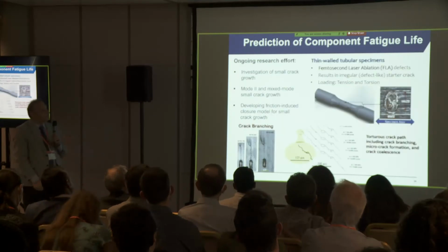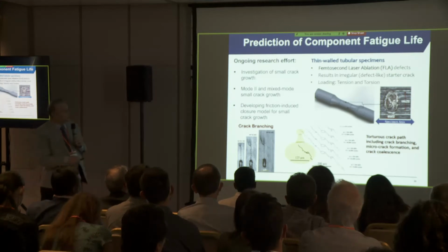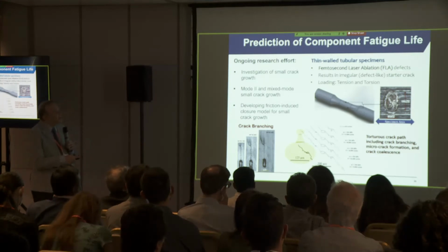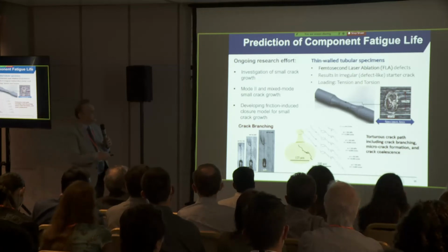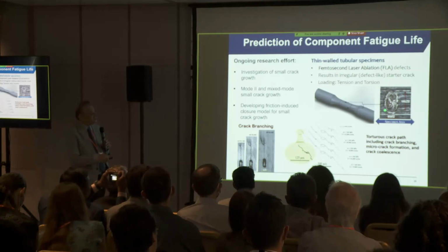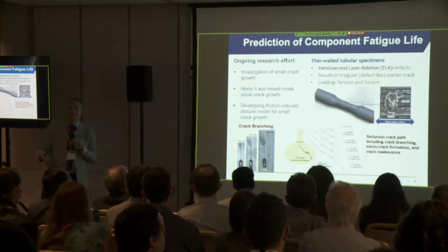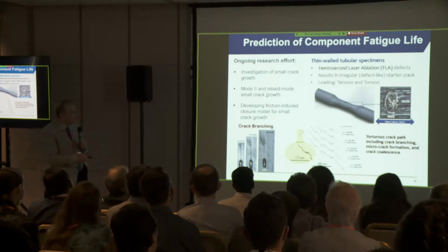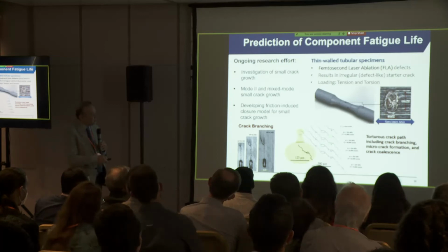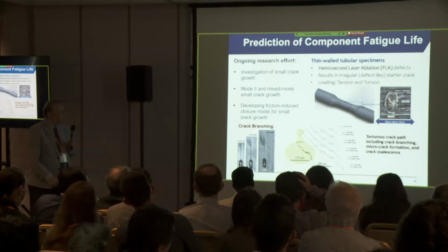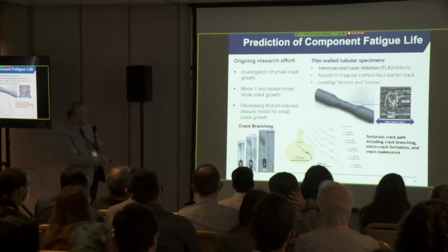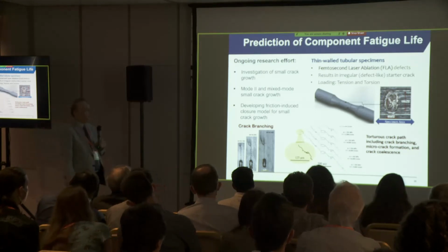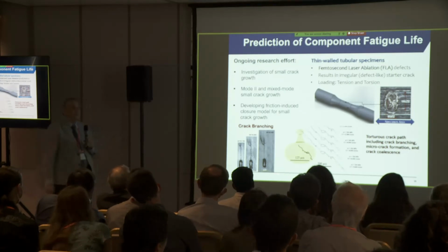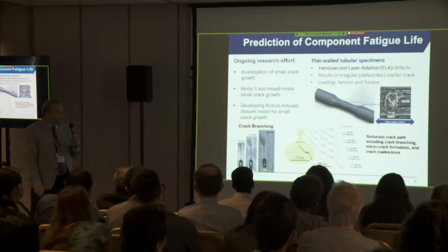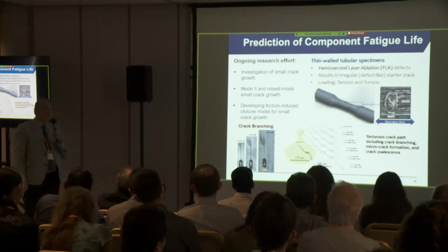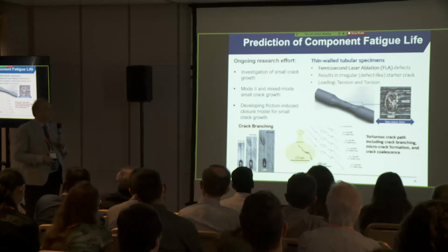So this is the research I'm currently working on with my group on small crack growth. We have used FLA, femtosecond laser ablation, that creates a structure of defects that mimic or are very similar to defects in additive manufacturing. And these are the type of crack growth that you see. Again, these are very small cracks growing, and different phenomena like crack branching and tortuous crack path are present, and we are trying to model these aspects of crack growth for application in a fracture mechanics framework for more robust use of additive manufactured metals.